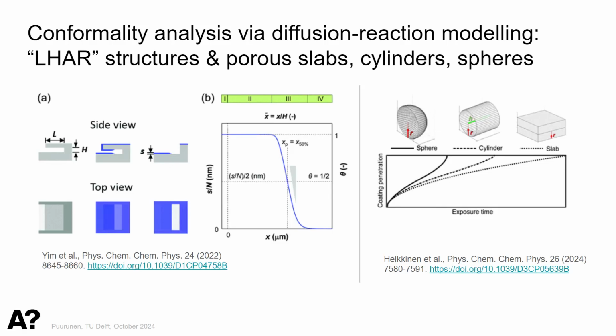So there's a paper in Physical Chemistry Chemical Physics, where in addition to the slab modeling, which corresponds to the LHAR, that means lateral high aspect ratio test structure, they are basically the same, and how the coating penetrates as a square root function of exposure time, that's known, but then this sphere and cylinder modeling, that's more new. Maybe not surprising how it came up, but now those equations are out.